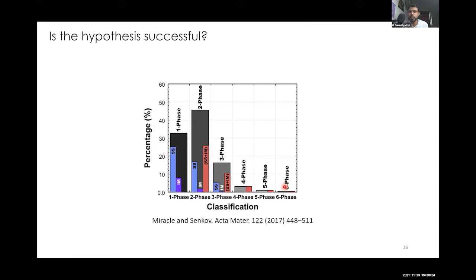So your idea of stabilizing one single solid solution over intermetallic phases has not worked out in all the cases. That is at least true from this diagram. Okay. There are multiple phases coming in depending on what alloy system we chose. Even in the single phase, we think that we are stabilizing a solid solution only, but there are cases where we get single phase intermetallic phases also. So stabilizing a single phase solid solution by increasing the configurational entropy is not working irrespective of which 5 elements, 6 elements we choose. Okay, it depends on what elements we choose.